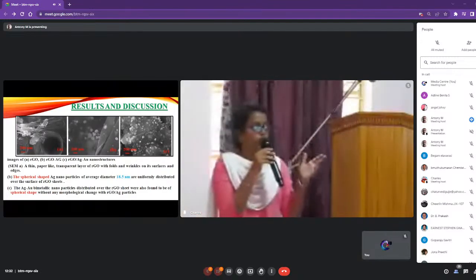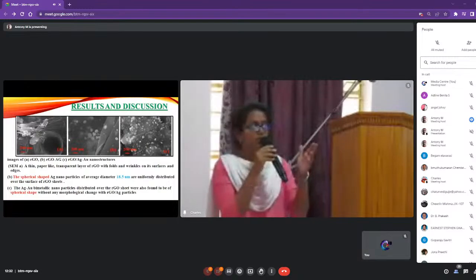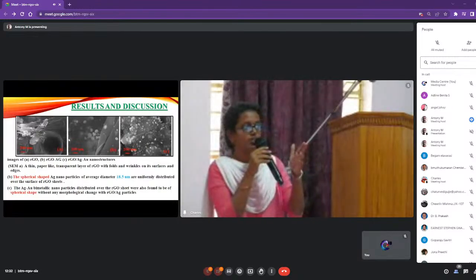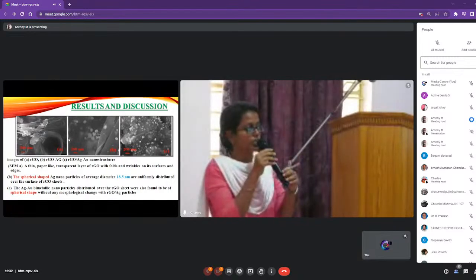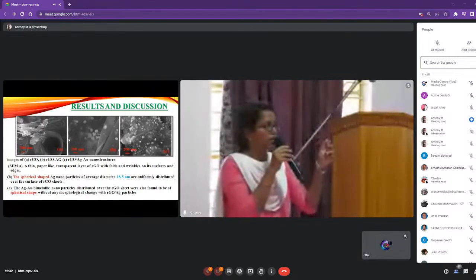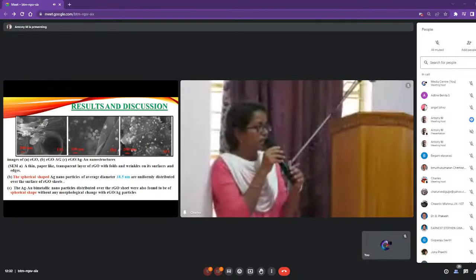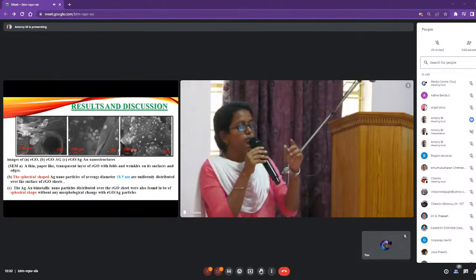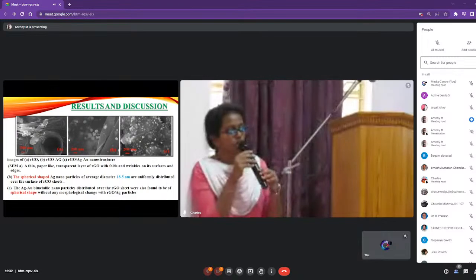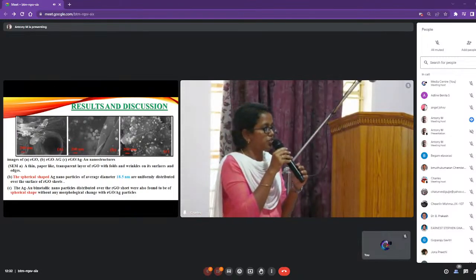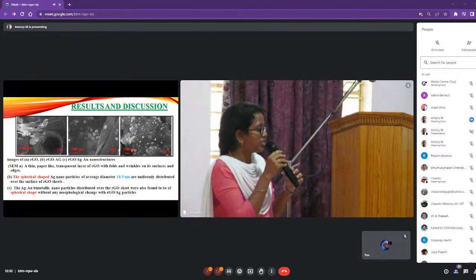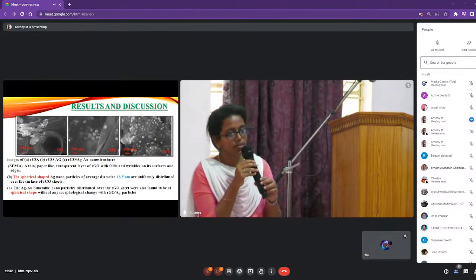The SEM analysis of reduced graphene oxide, reduced graphene oxide silver nanocomposite, and reduced graphene oxide silver and gold nanocomposite. The first one is RGO, which is a thin layer, and the second one is RGO-Ag, which is spherical in shape, and the third one is RGO-Ag-Au, which is also spherical in shape, and the second one has a diameter of 18.5 nanometers.